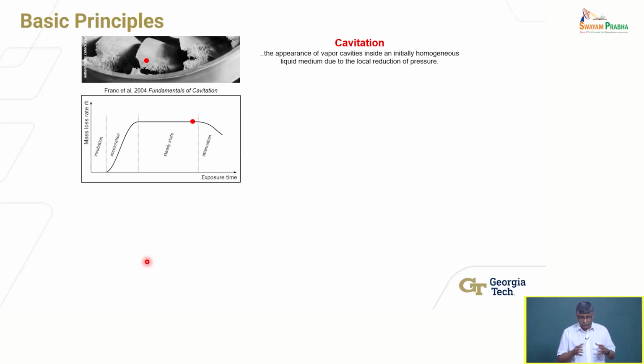These vapor bubbles, when they collapse, generate a shock wave. They also generate something called microjets. So you have water around it, and it generates microjets. The combination of these two things can be strong enough to actually modify the surface. Not just modify, wear it, which is what happened in these marine applications. So what you see here in this picture is basically cavitation erosion. You're eroding the material away where these bubbles collapse.